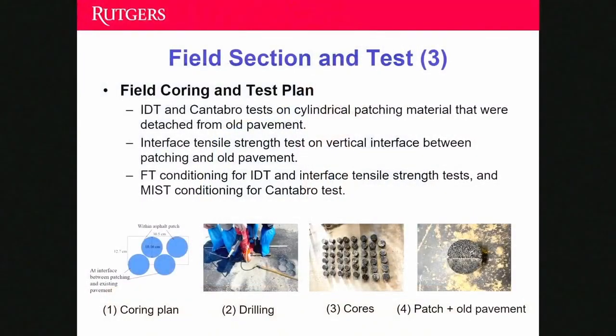And as shown in the first picture, we took 2 field cores within the asphalt patch area. So in this case, we can get 2 field cores with the horizontal interface between the patch and the old pavement. And we also took another 2 field cores at the edge. So in this case, we can get 2 field cores that have the vertical interface between patching and the old pavement. And if we look at the last picture, it was the patching material with the vertical interface.